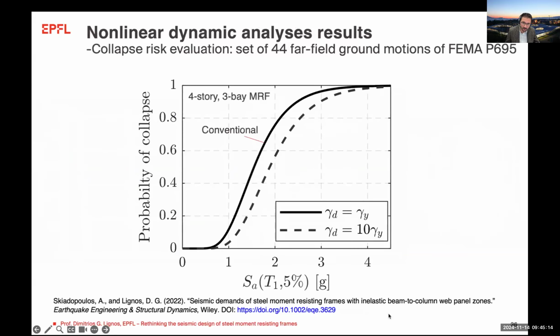And essentially what we are learning from this is that if you're looking at an indicative case such as a 4-story, 3-bay moment-resisting frame, if you are looking at code-compliant design versus highly dissipative, and highly dissipative in this case would be a design that the panel zone goes to 10 gamma Y, you have a benefit when you're looking at the probability of collapse, that is being reduced by about 50%.